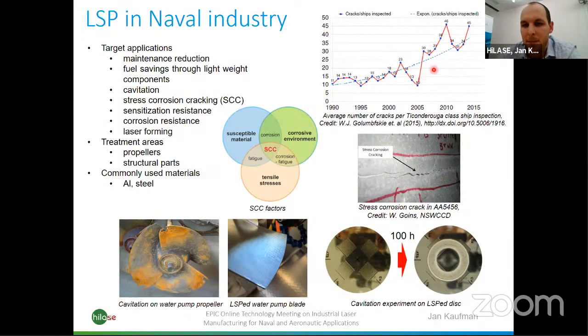So this is where LSP can help a lot, because in order for stress corrosion cracking to develop, you need three components, which are a susceptible material, a corrosive environment, and tensile stresses. And LSP can help with the tensile stresses. It can change them into compressive stresses, which renders the whole stress corrosion cracking process basically unable to work.